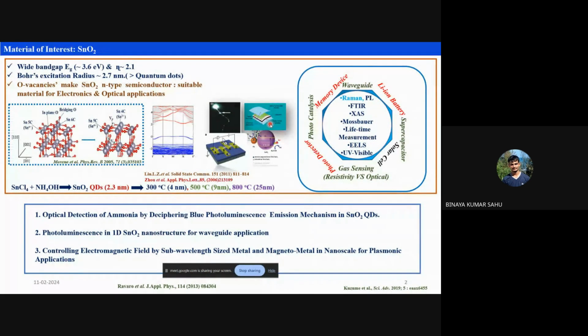For that, I have to have concrete knowledge of spectroscopic techniques. There are various spectroscopic techniques like Raman, PL, which stands for photoluminescence, then Fourier transform infrared spectroscopy, XAS, which is X-ray absorption spectroscopy, Mossbauer, and lifetime measurement. I may not talk about all the spectroscopic techniques to scrutinize defects in my material, but I will be talking about various techniques, especially photoluminescence, lifetime measurement, UV-visible, and Raman.